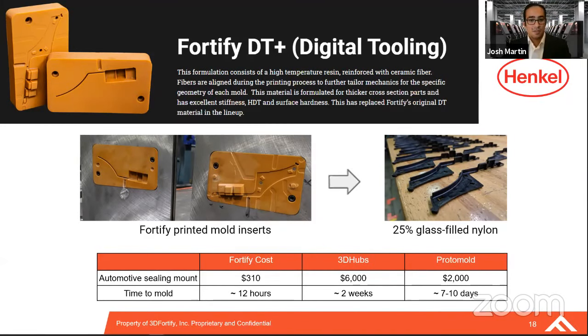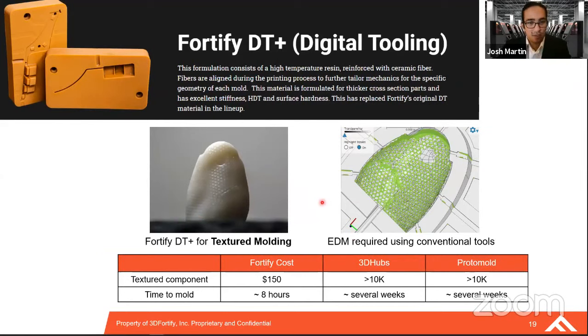And one more example on sort of these tooling textures is if you look at what would typically be required to produce high resolution tools. In some cases, it's more than just a 3-axis or 5-axis CNC would provide. You may have to turn to EDM machining, which is very expensive, takes a tremendous amount of time. And that is something that leverages the 3D printing resolution, where we're able to essentially print these programs or these textures and contours into our tools very effectively and without too much hassle to the user.